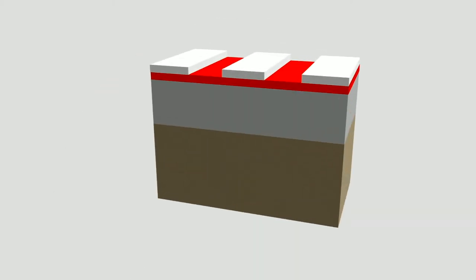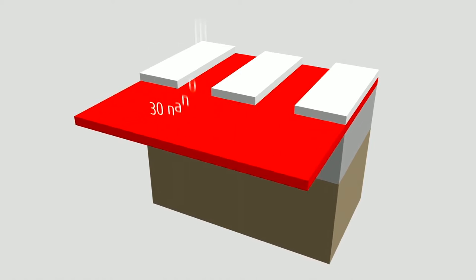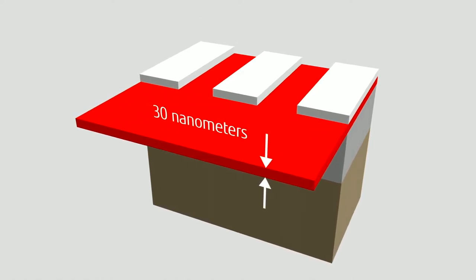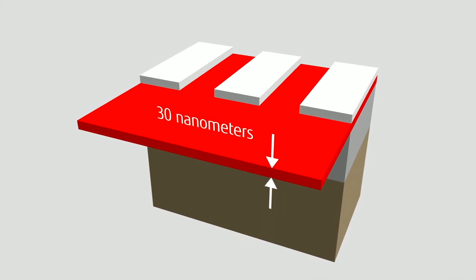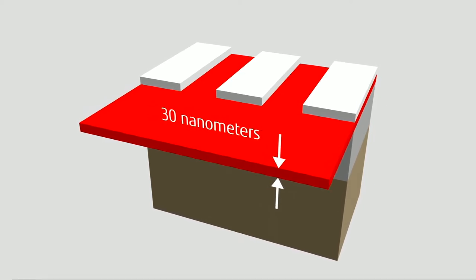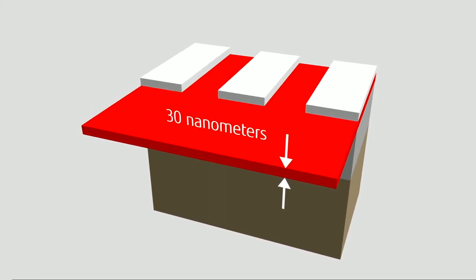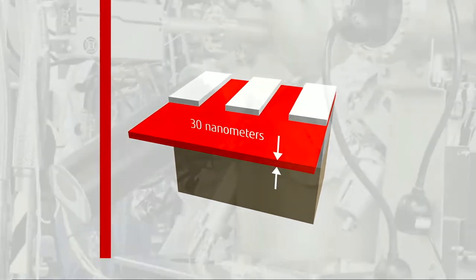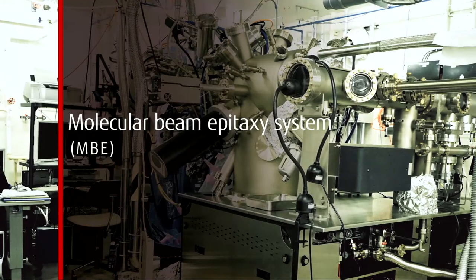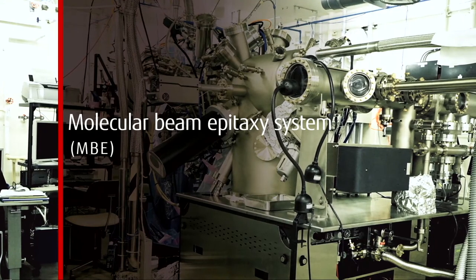For example, the thickness of the crystal layer of aluminum gallium arsenide that serves as the HEMT's electron supply layer is only 30 nanometers. A molecular beam epitaxial system controls the thickness of this layer to be equal and prevents the material from mixing with the materials in layers above and below.